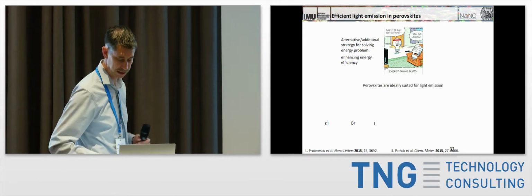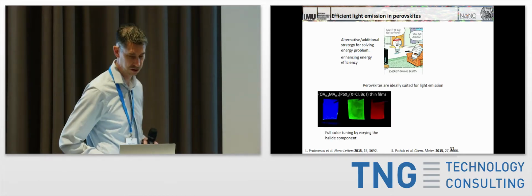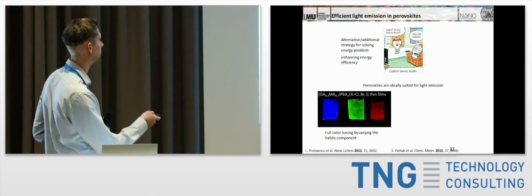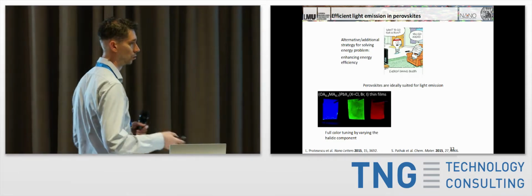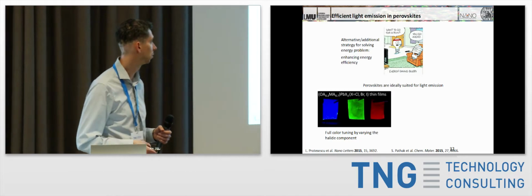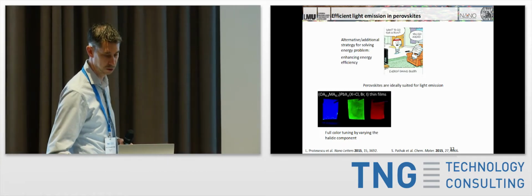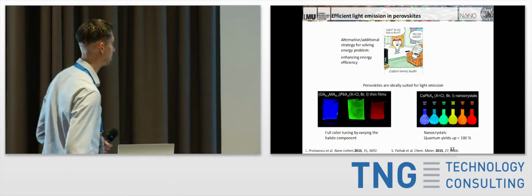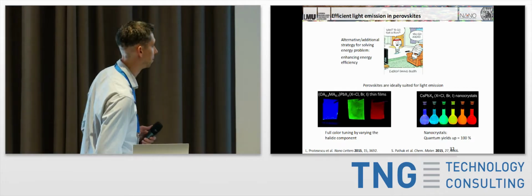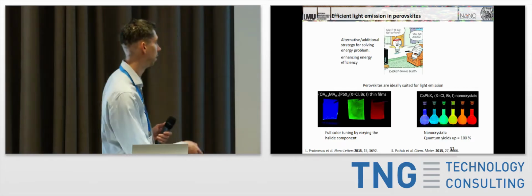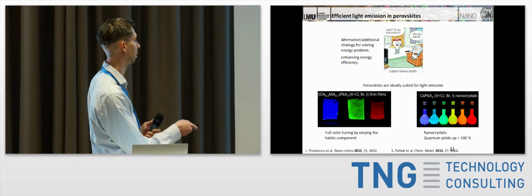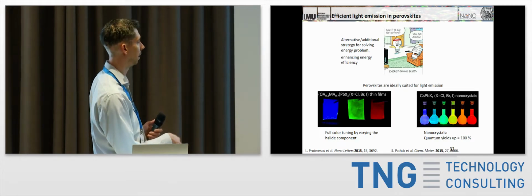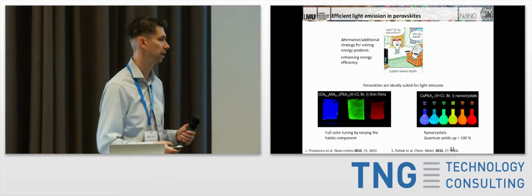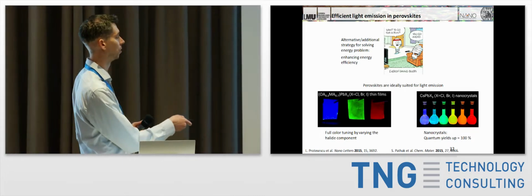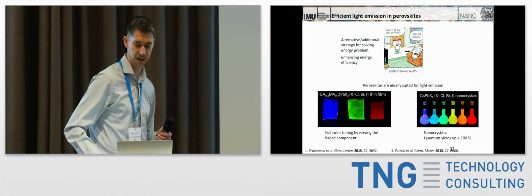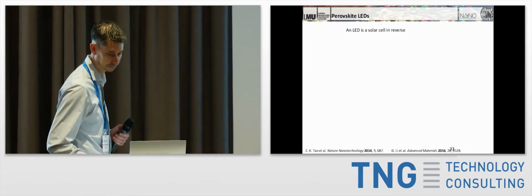And so perovskites themselves are ideally suited for light emission. Basically, we talked about that before, showing that as you tune the band gap, you can tune the absorption, but you can also tune the emission of these. So they can emit anywhere between the blue and the red. And actually, if you go into making nanocrystals out of these, it turns out that they're extremely efficient in how well they produce light. So essentially, if they absorb a UV photon, with yields of nearly 100% they convert this into a photon of a different energy. And so obviously, you can mix this up now to make very nice LEDs.